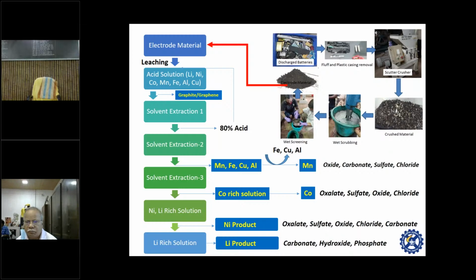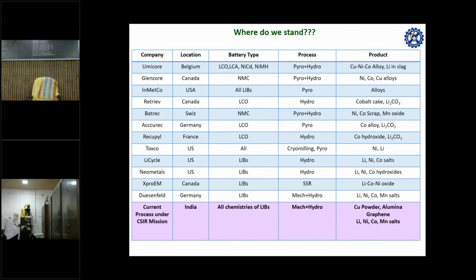The theme of the presentation is that we grind the battery and separate the powder. This is by manual separation. We take the powders and do the leaching of it. By 3-stage solvent extraction, we make manganese, cobalt, nickel, and lithium products in different forms, and then the acid is recycled back, and the carbon is made into graphene. And this process has been patented by NML.